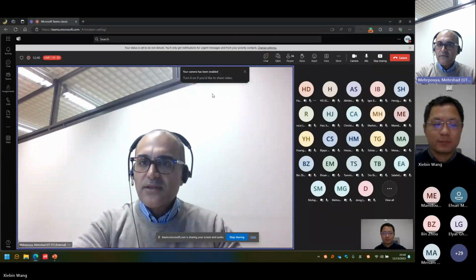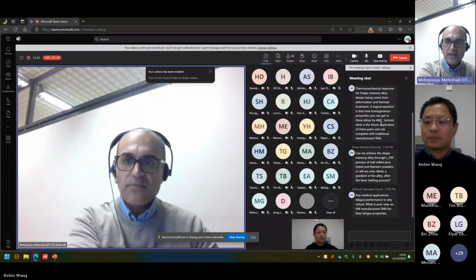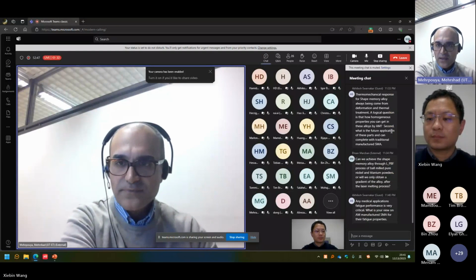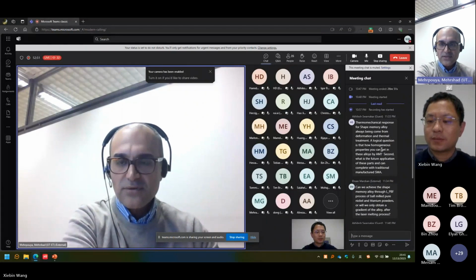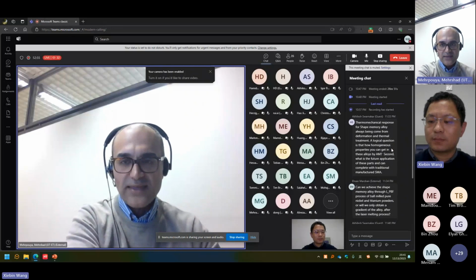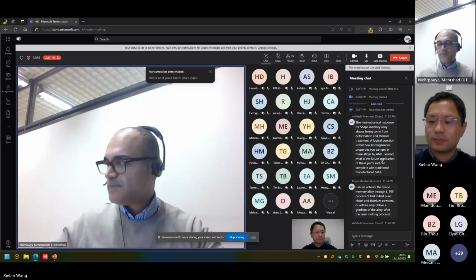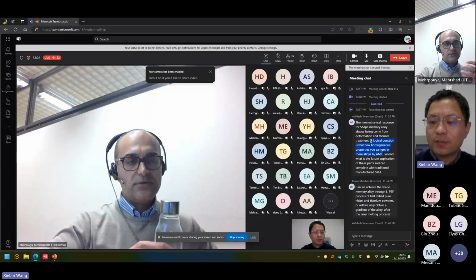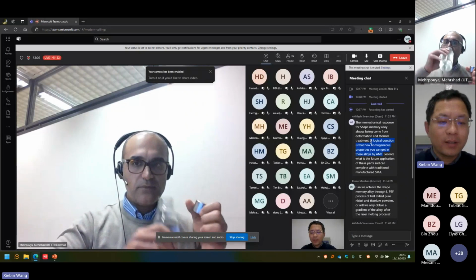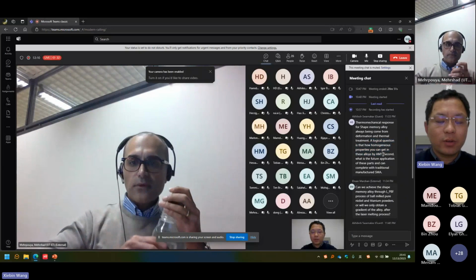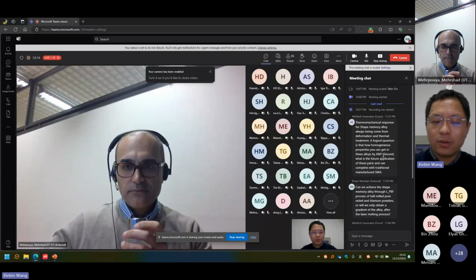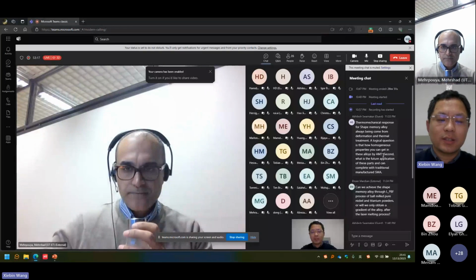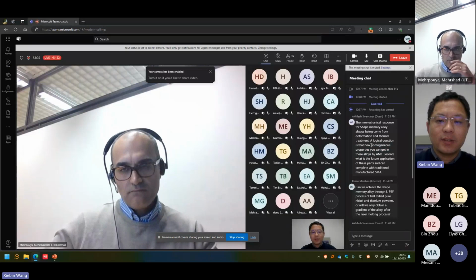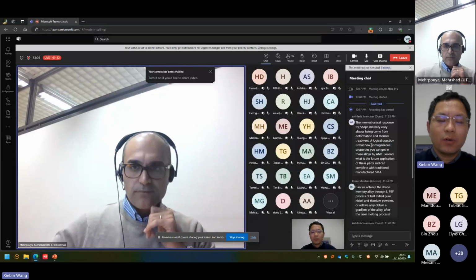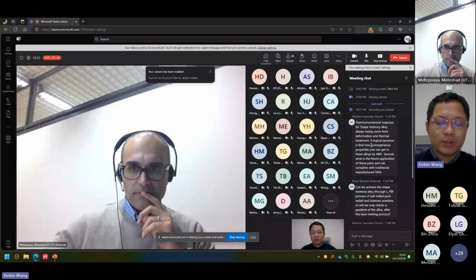The first audience asks: the thermomechanical response of shape memory alloys always comes from deformation and thermal treatment, so a logical question is how homogeneous properties you can get in this alloy by the additive manufacturing process. For this question, actually after solution treatment for the binary alloys, it's not a problem. You get a very homogeneous material. But for the in situ alloy, like what we did, nickel, titanium, niobium, it's not easy to get a homogeneous structure. But if you use pre-alloyed powders, that's not a problem. If you always use pre-alloyed powders, you will get a very homogeneous microstructure.